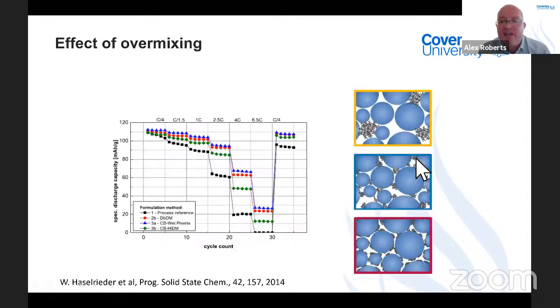If we go back to the overmixing now, we can see here three considerations, three mixing scenarios depicted in the cartoons on the right-hand side. Now, if you look at these in the top image, you can see the large blue balls being the active material, and then the gray black part being the carbon black. Now, this carbon black comes as a heavily agglomerated powder, but is made up of sort of tens of nanometer or smaller size individual particles that are agglomerated. If you don't disperse it well enough, you're going to get a situation like you see in the first image,